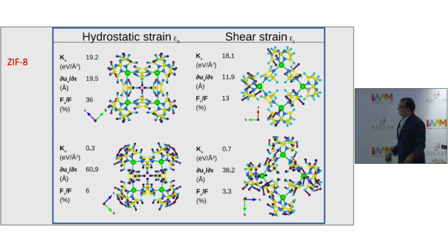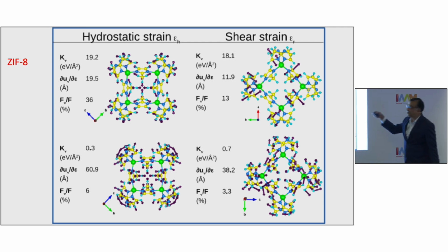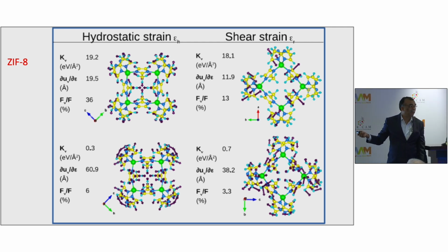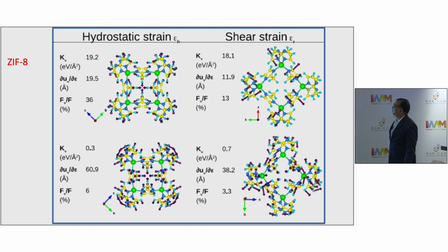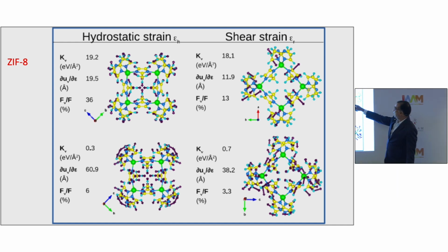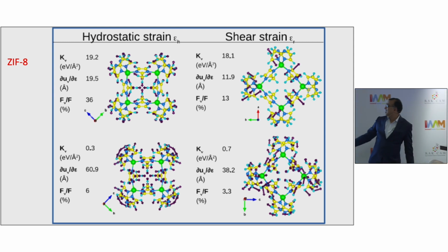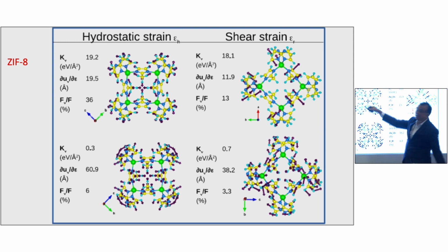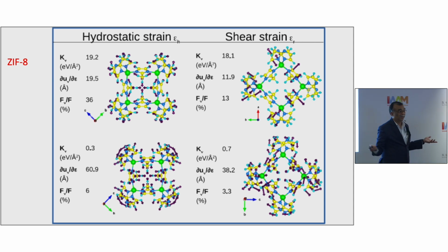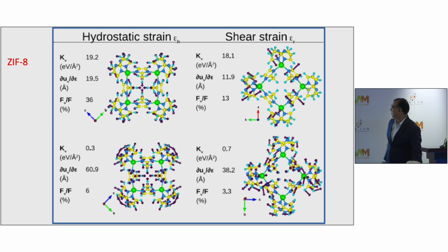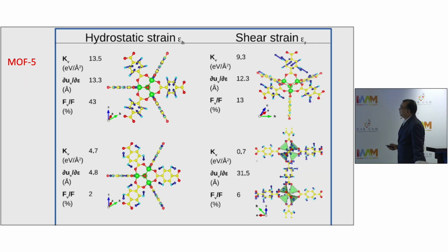Okay, so we have, of course, access to a lot more information. On the left column, we have the modes which contribute to hydrostatic flexibility, and the one on the right gives you shear flexibility, and you will see the shear one has lower symmetry modes, whereas these displacements maintain the symmetry of your lattice because hydrostatic strain doesn't break the symmetry. Okay, so all this fits beautifully well.